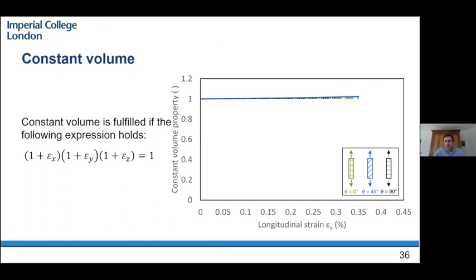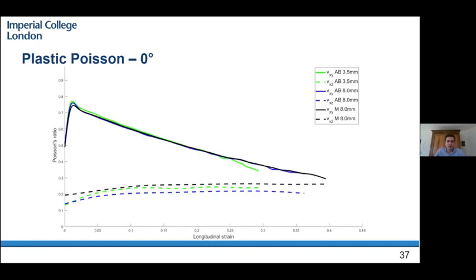To indicate a little bit more, in the elastic domain, the through thickness measurements were too noisy, so there's a very big signal to noise ratio in this domain. So in the elastic domain, it was not really usable, but for the plastic domains, we were able to get reasonable results. For example, you can see here the dashed lines on the bottom are the 0-degree direction Poisson's ratio in the through thickness direction. So we were still able to get reasonable results out of it.